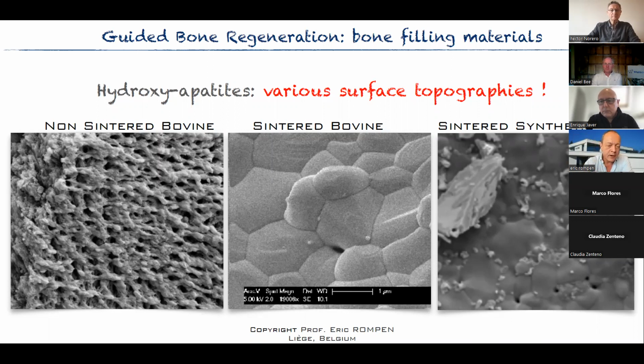On the left side, we have a non-sintered bovine hydroxyapatite. This is actually the Bio-Oss, very rough. And that is why this material is very osteoconductive. That is why this material is excellent for getting a very high osteoconductivity. It's not excellent for everything, and we will come back to that later on. But for osteoconductivity, this is the best material because it is the roughest material on the market at the moment.